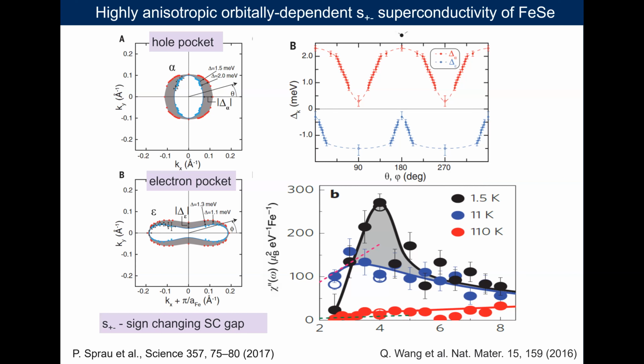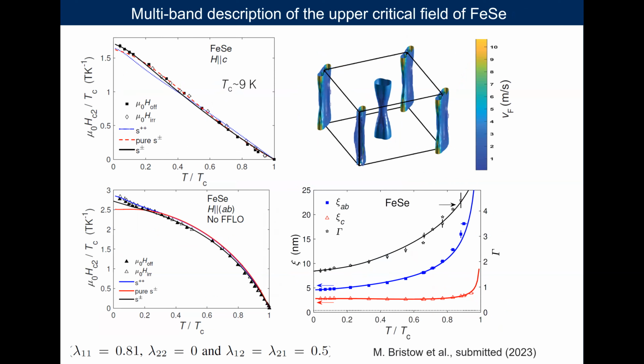We show that the peak in the imaginary part of spin susceptibility is enhanced when the system enters the superconducting phase, as a signature of spin fluctuation mediated superconductivity. To understand the upper critical field, here are some of our recent data.